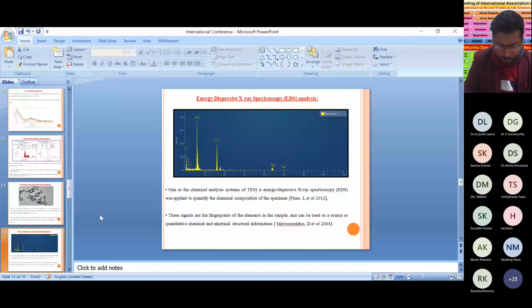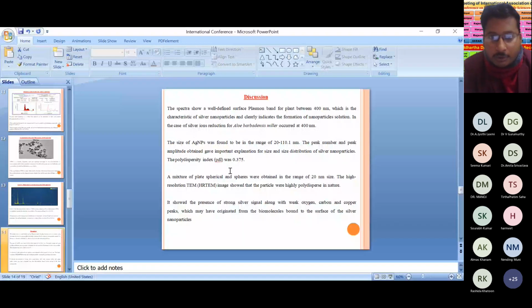Discussion point: the spectra show a well-defined surface plasmon band for the plant extract at around 400 nanometers, which is characteristic of silver nanoparticles and clearly indicates the formation of a nanoparticle solution. In the case of silver ion reduction by aloe vera, it occurred at 400 nanometers. The size of nanoparticles by DLS was found to be in the range of 20 to 110.1 nanometers. The peak number and peak amplitude obtained gave important information on the size and size distribution of the silver nanoparticles.